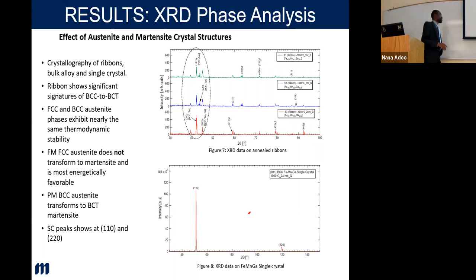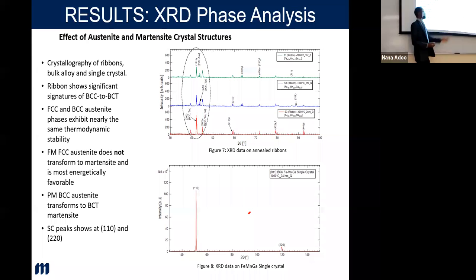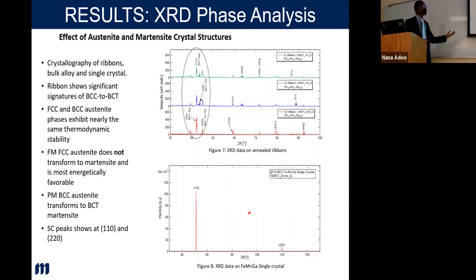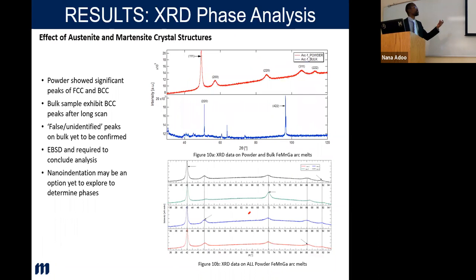To get the orientation of what we're doing from the test so far, I got a single crystal and tested it and got to know where the peaks are, and the single crystal actually shows pure BCC, for me to know what is happening there and correlate it. So going forward, my next goal is to pick these peaks, match them, or revisit the XRD, and then see which peaks are producing the noise.